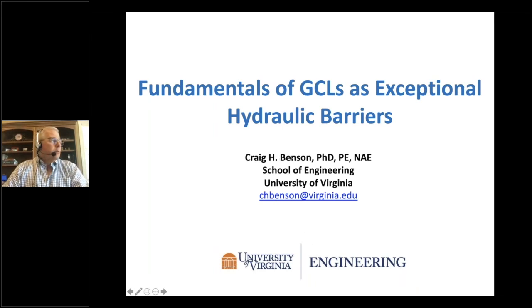What you can do, though, if you're doing design and you want to use a typical value, what I might use in design, I'd use a free solution diffusion coefficient. I'd use a tortuosity of about 0.2, so it's about 20% of the free solution diffusion coefficient. That's really conservative. The actual diffusion coefficient for the bentonite is going to be lower.